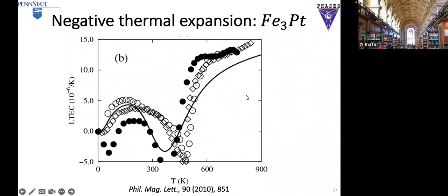So this is thermal expansion plotted as a function of temperature at ambient pressure. As you can see, the symbols are from experiments, the lines from the prediction of the model, all from DFT calculation without any models beyond the DFT. So what you see here is that the volume increases, then maximizes, then starts to decrease, becomes negative, then becomes minimum, then goes up again, right? That's the zero case. This is called the Invar effect, which was discovered in 1897.